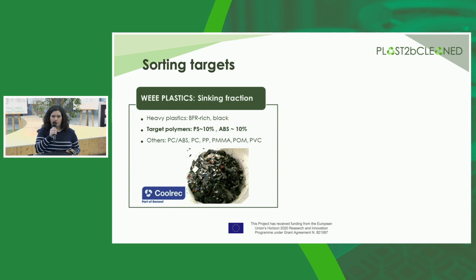It is composed of heavy plastics. It is rich in brominated flame retardants, and as you can see in the picture, most of these plastics are dark or black. In this WEEE stream, we can expect 10% of polystyrene and also 10% of ABS on average. So this is the content of our target polymers to improve the sorting. But there are other polymers that could be of interest for the recyclers, like the blend PC-ABS or PC. But there are other polymers that can jeopardize the sorting of the target polymers for the Plast2bCleaned project.